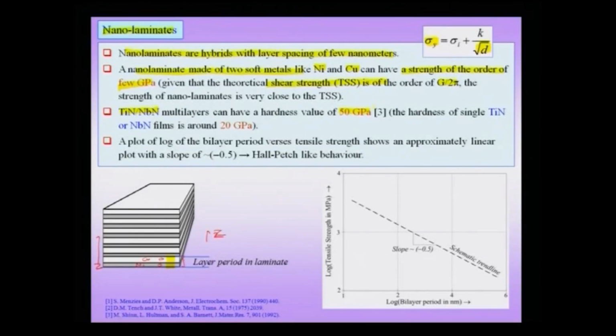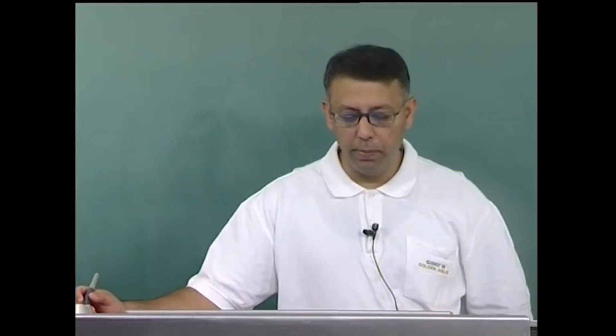And if you note the hardness of individual layers like the titanium nitride and niobium nitride, that is much lesser than this value of 50 GPa. The important point to note in this context is that not only are we getting this kind of a hardening effect, but suppose I study the hardening effect as a function of the bilayer period, and for now I assume that the individual layers made up of either titanium nitride or niobium nitride, or in the nickel copper system either made of nickel and copper, are equal thickness.